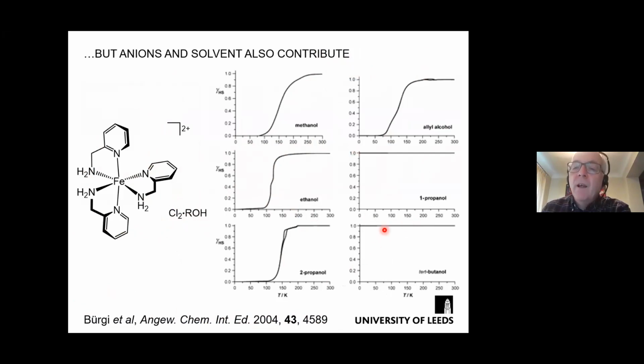2 of them just stayed high spin at all temperatures. They did no switching. The methanol solvate is very gradual. The ethanol one has 2 steps. The isopropanol solvate has a more complicated switching up here. So the switching properties you see change a lot depending on the solvent. And I should say that all 6 of these materials have the same basic crystal structure, the same basic lattice. They're not perfectly isostructural, but the packing is the same in each case.